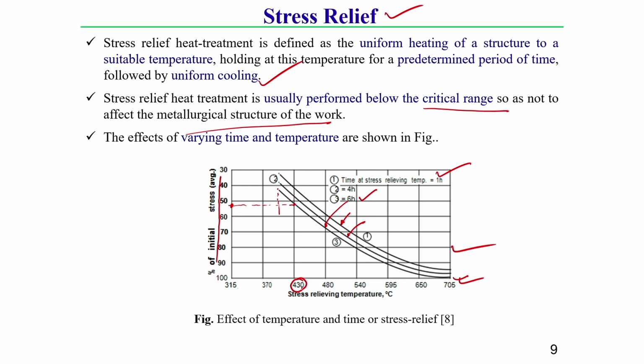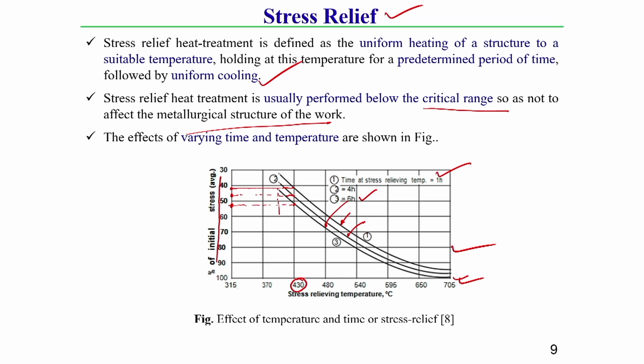If you hold this 430 degree centigrade temperature for 4 hours, then you can see the removal of residual stress is around 47%. Okay. If the time is further less, then the residual stress relief also further decreases. That means residual stress relief is around 40%. So, what we can observe, for a particular temperature, if your soaking time increases, the percentage of reduction of residual stress increases. This you should keep in mind.